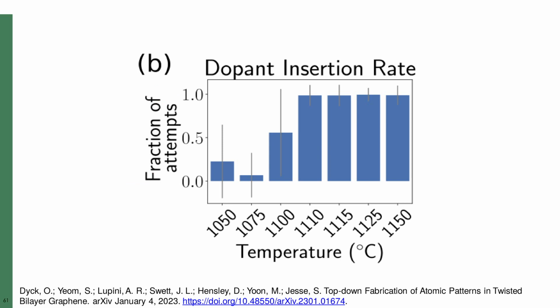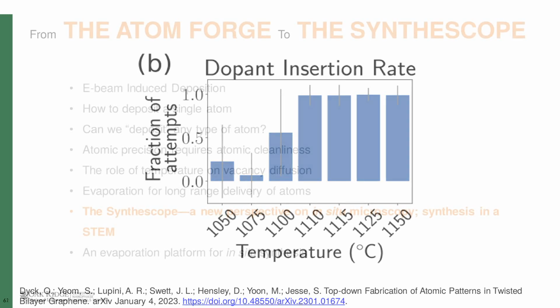We see very clearly that at about 1100 degrees Celsius, we switch from mostly milling holes to inserting dopants. This is right around the melting temperature for bulk copper. So indeed, we are evaporating or atomizing our source material, it is diffusing across the sample, and we can then pattern these atoms into the substrate. Chrome has a much higher melting point than copper, so we are getting copper atoms, but the idea works.